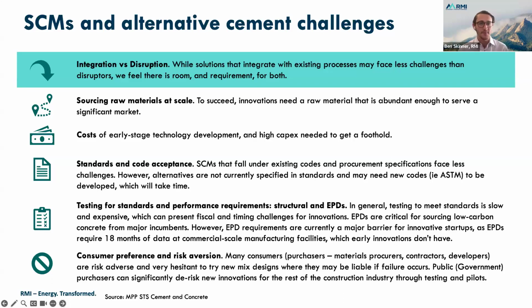It is worth noting that some of these new cement blends, such as Sublime, are actually already certified under ASTM C1157, whereas Brimstone is certified under ASTM C150. And so reaching those ASTM certifications is one part of things, but of course needing to ultimately get onto the approved materials list of DOTs is another. Testing for standards and performance requirements and the increase in EPDs is really critical here. It's challenging to move through the EPD process when you are a startup, as they often require 18 months of data at commercial scale manufacturing facilities, which most startups don't have.